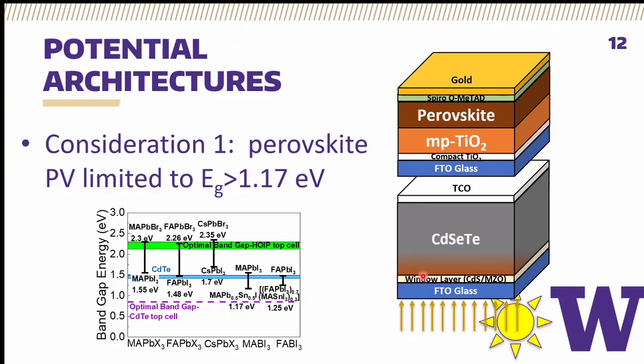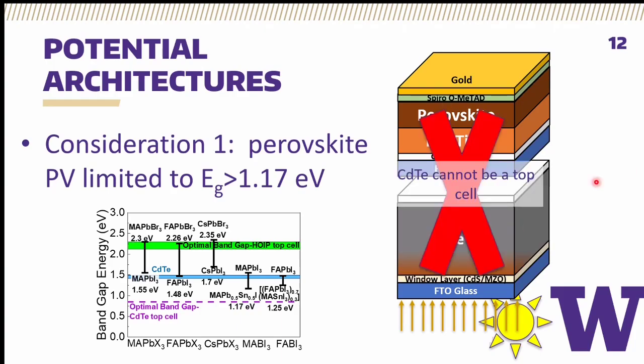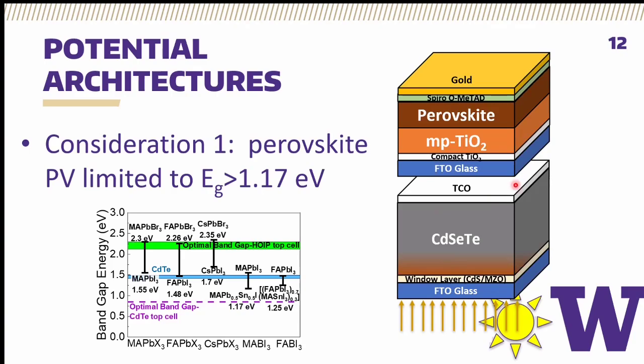So, with this in mind, potential architecture considerations, we wanted to rule out as many of the architectures as possible based on just design constraints given the current state of perovskite and CdTe fields. And the first one, and it's kind of a major unfortunate blow, is that perovskites cannot be used in this sort of top cell arrangement with CdTe. The reason is you really want this arrangement here, where CdTe is the top cell, even though it's shown on the bottom here, light is shining from below in this instance. You really do want the cadmium telluride to be the quote-unquote top cell, because it has a wider band gap.